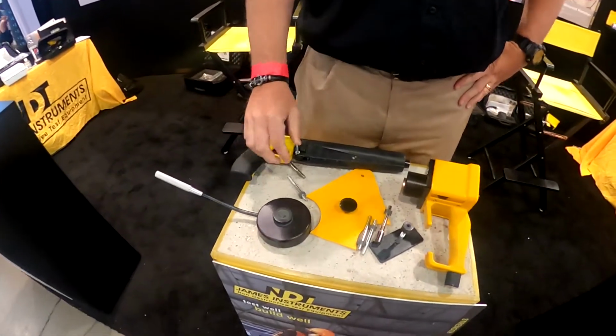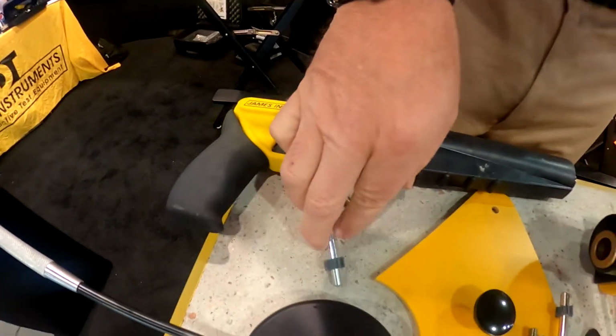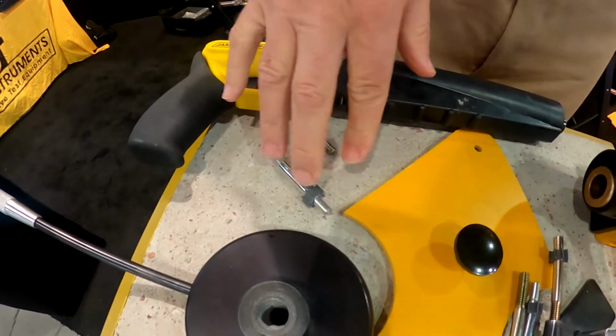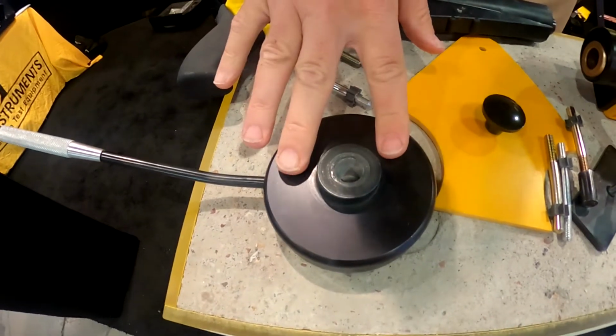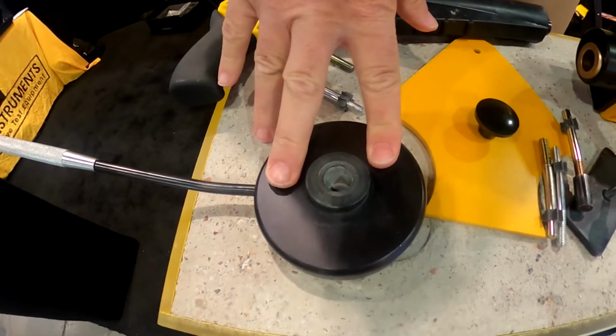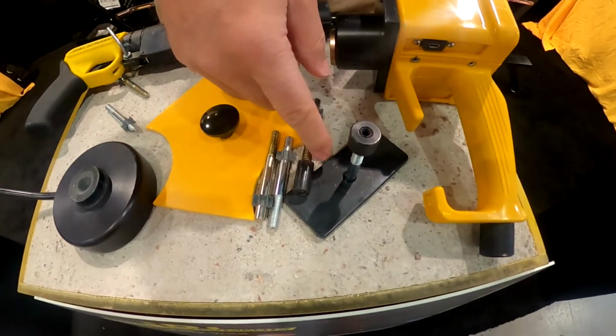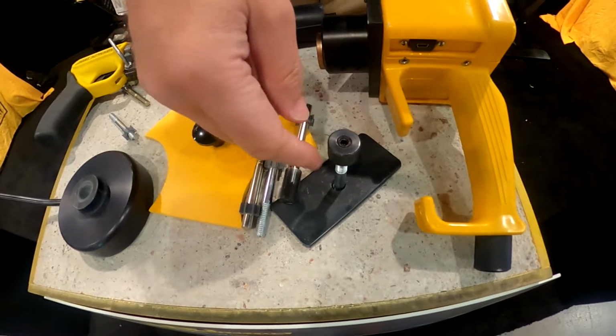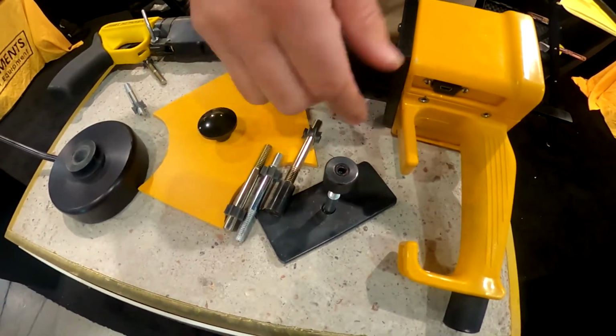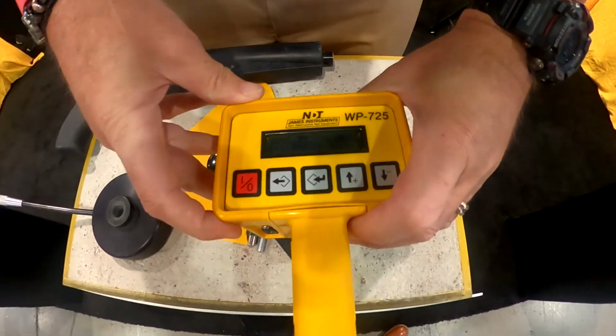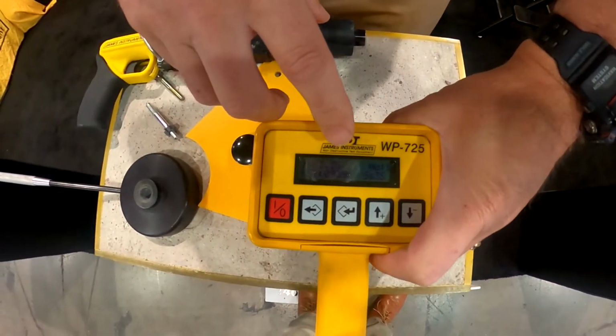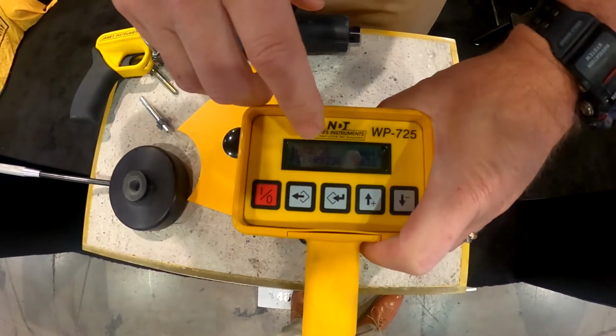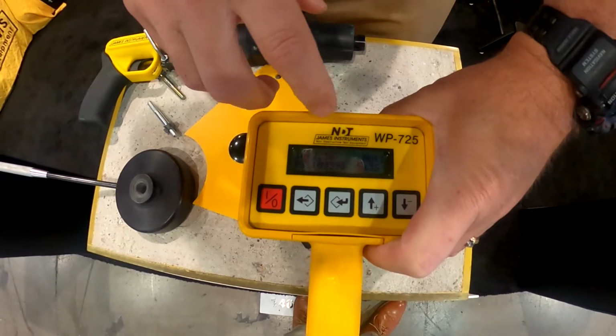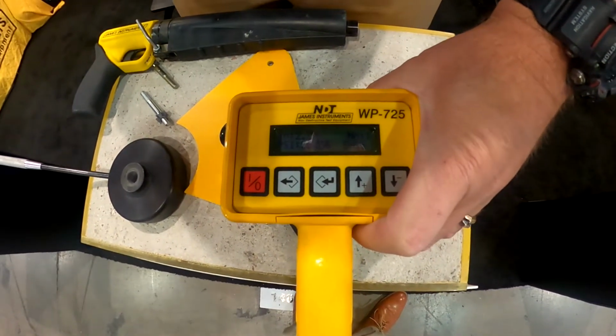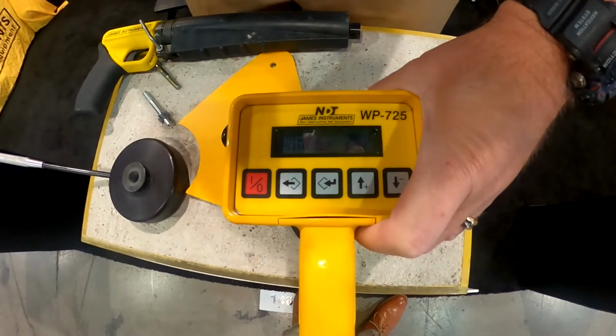One of our flagship products is the Windsor Probe system. The driver unit here fires this probe into the material under test, typically concrete, and has this safety device that won't allow the probe to pass through in case it's very poor concrete. The depth that the probe goes into the concrete corresponds to the compressive strength. So the deeper it goes, the lower the strength of the concrete. This electronic reader reads the strength of the concrete after the probe's been fired into the material. This unit is now reading 9,000 psi concrete, and the entire system can test compressive strengths up to 17,000 psi.